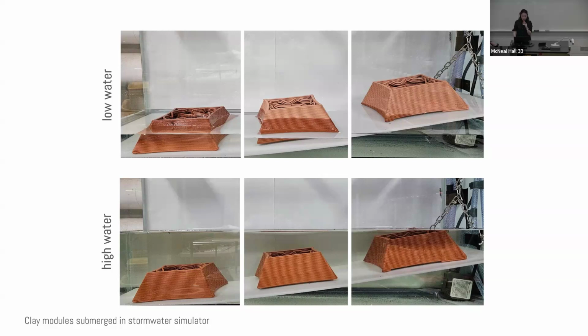The top image shows the low water level. So that's when the water has already gone down to downstream level, where the pond might be on a typical day, while the bottom image shows the high water level simulating a storm event. So as you can see, one module, the one on the bottom, is always submerged. The middle one is always partially submerged. And the top one is only submerged and wet during stormwater events.